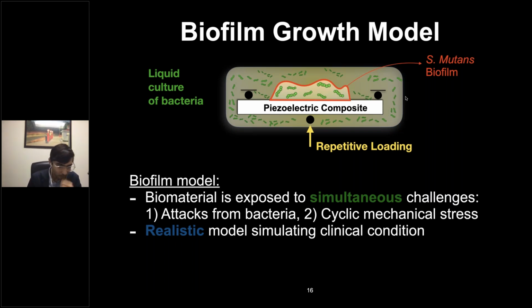We were verifying that our material preparation was good to go before doing any microbiology. The second step was to show that this material exhibits antibacterial effects. So we made a new biofilm growth model, preparing beams and submerging them into bacterial culture. We used Streptococcus mutans microorganisms. We picked this strain because, first, it's acidogenic, meaning it produces acids and esterases known to degrade biomaterials. Second, it's the keystone organism found in dental caries, the key driver of dental caries. Third, it's highly well-known and studied, a strain highly understood by the community.